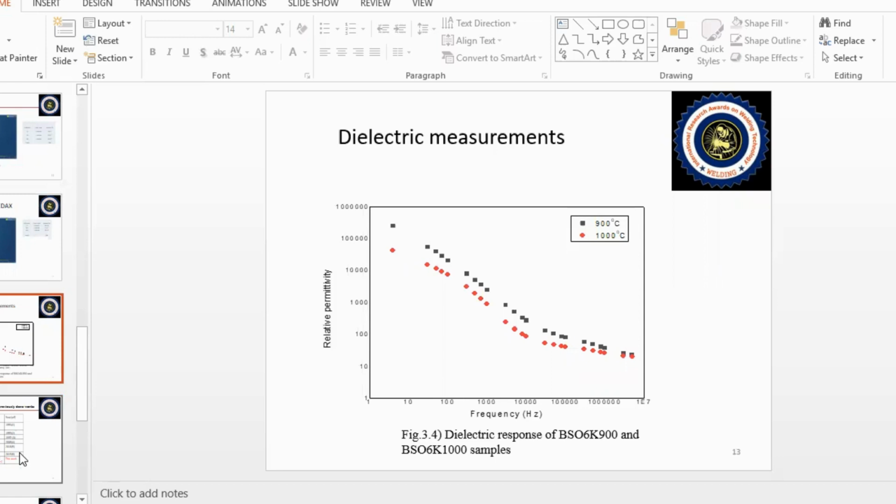dielectric constant. When the sintering temperature increases, the grain conductivity and the crystallinity of the samples are enhanced, leading to conductive behavior in the samples. Hence, the magnitude of permittivity decreases with an increase in sintering temperature. Also, the crystallinity leads to a large relaxation time for the charge carriers. High temperature sintering of perovskite oxide results in high oxygen deficiency, which causes an increase in conductivity.